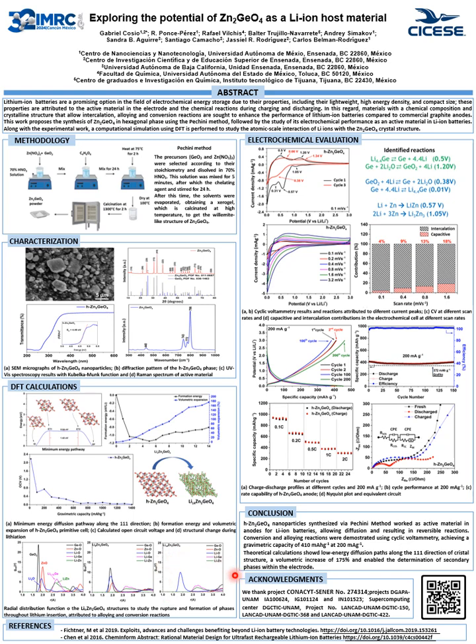In conclusion, it can be confirmed that zinc germanate nanoparticles synthesized via the Pechini method can be effectively used as active material in lithium-ion batteries, facilitating diffusion and reversible conversion and alloying reactions. Additionally, theoretical calculations showed low ion diffusion energies and a volumetric expansion of 175%, which is moderate compared to the volumetric expansion of germanium oxide, and revealed potential secondary phases in the electrode.